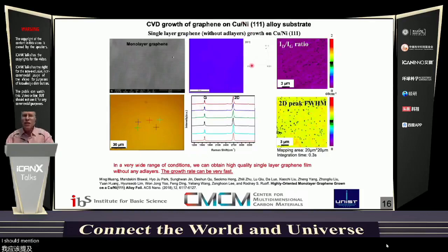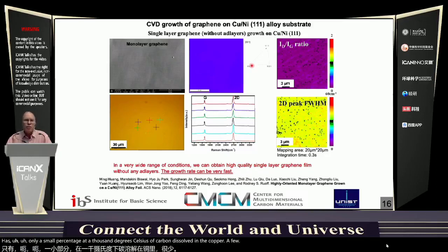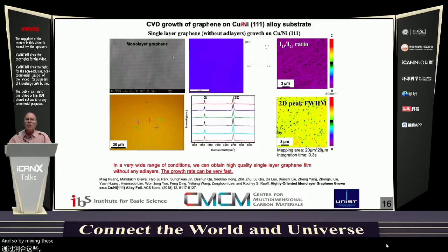I should mention that the binary phase diagram of copper and carbon has only a small percentage at 1,000 degrees Celsius of carbon dissolved in the copper, a few parts per million. But in contrast, nickel has a much higher solubility of carbon in the nickel, and that's going to be around 1 atomic percent at 1,000 degrees C. And so by mixing these elements with controlling the amount of nickel, it's possible to control the amount of carbon that will dissolve down into the substrate.